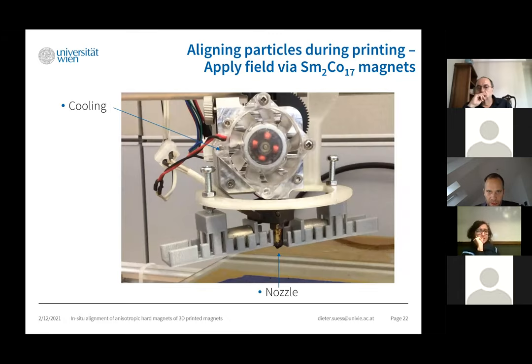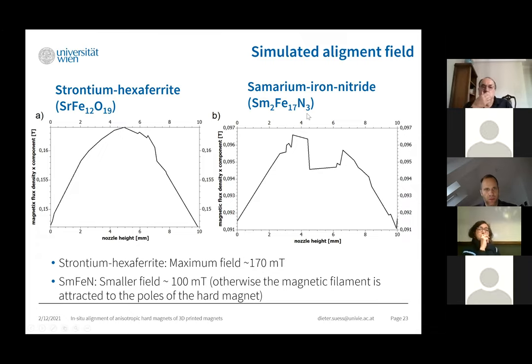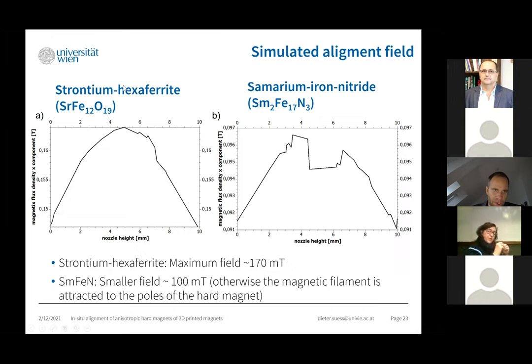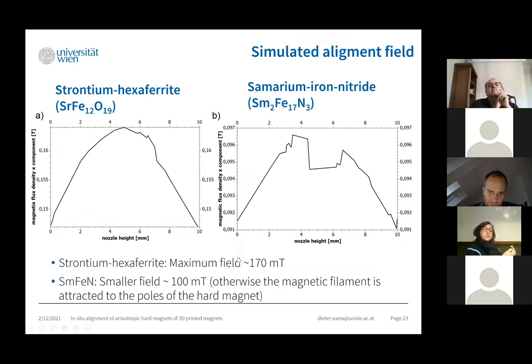And also depending on whether we print the hexaferrite, which has a small saturation magnetization, or samarium iron nitride, which has a high saturation magnetization, we had to use a different distance between the magnets in order to successfully print a magnet. For the strontium hexaferrite with small Ms, we can allow for fields of about 170 millitesla to align them and also to successfully print. If we produce larger fields, which was possible in our setup, the printing is not successful anymore. The magnetic filament is not put on the building platform, but sucked to the poles of the magnet. For the samarium iron nitride with a high Ms, we have to decrease the magnetic field.